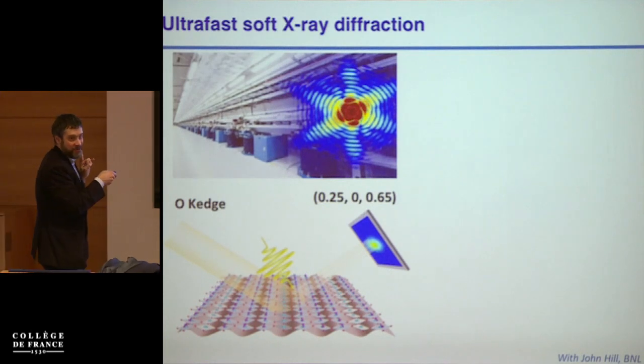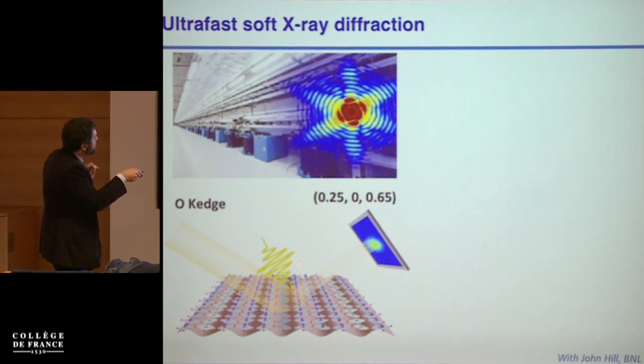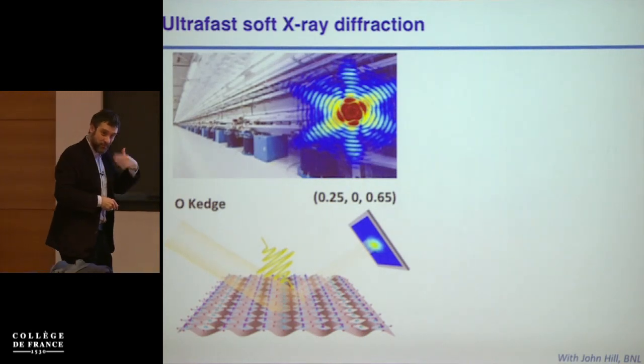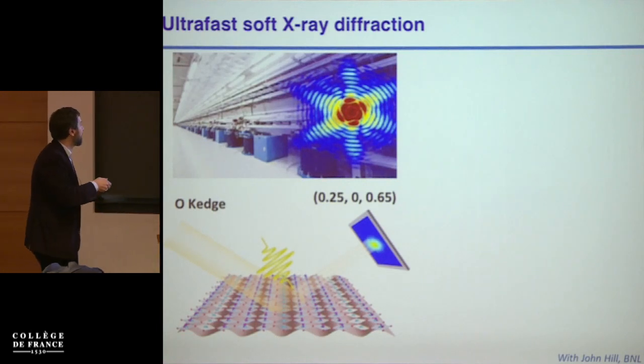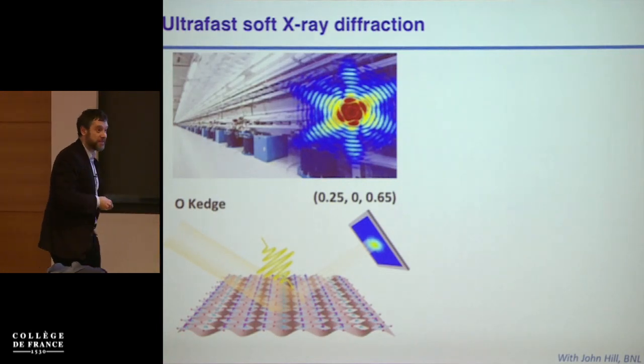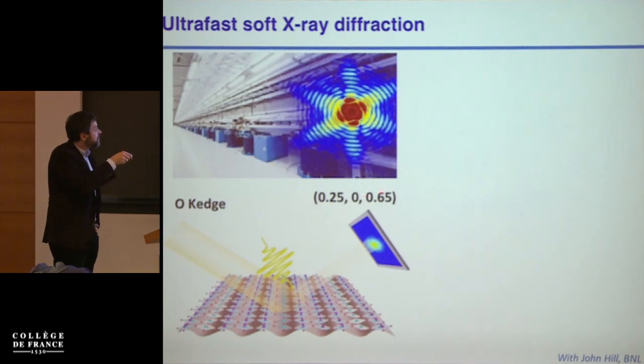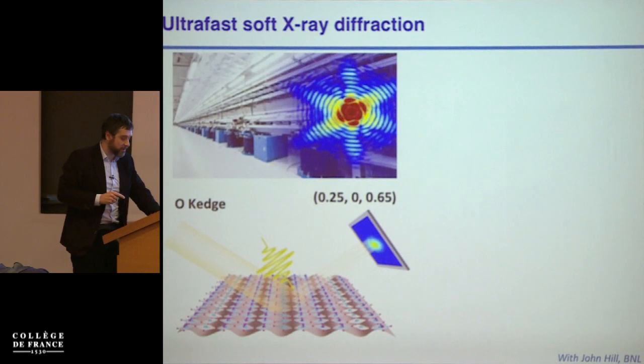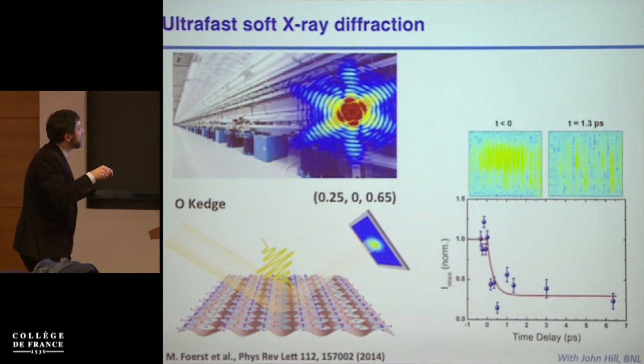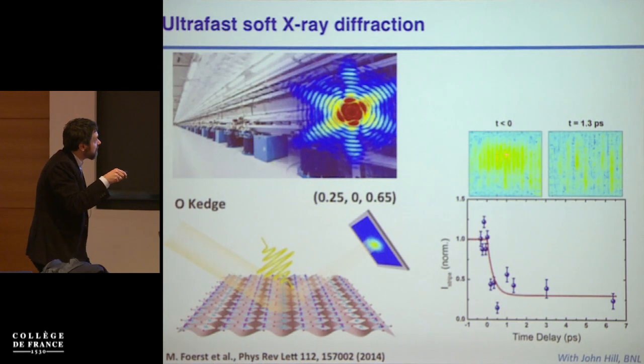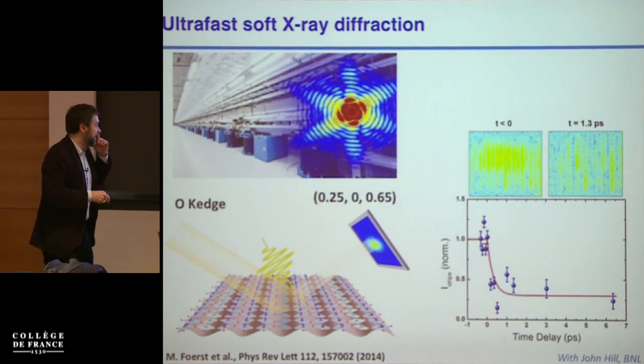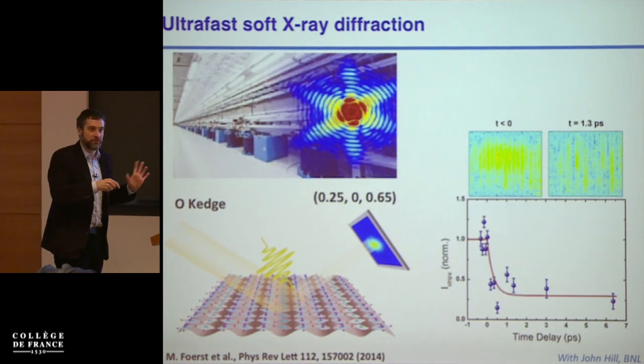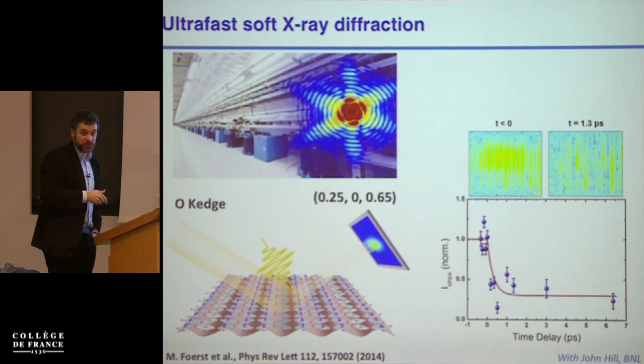After a year, we could do this experiment at the LCLS, where we pump the vibrational mode in LBCO, which is not the same as LESCO, but for the purposes of this talk we're going to make it look like it's the same. And then we probe the appearance of stripe order by this oxygen edge measurement at this superlattice peak. What we show is that by pumping this phonon, you start from a peak that is indicative of stripe order, and immediately after excitation, this peak goes to a level that is consistent with almost zero, a small number. So the stripe order is almost completely melted.